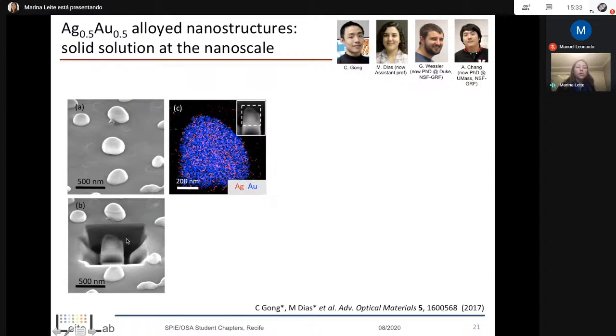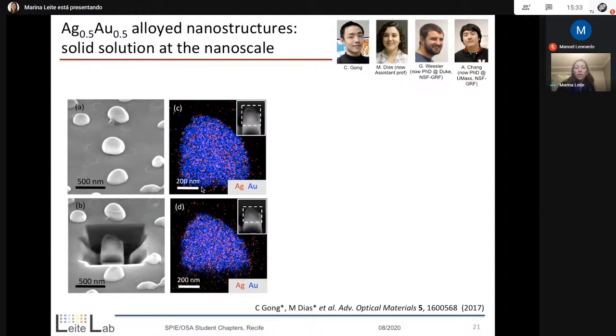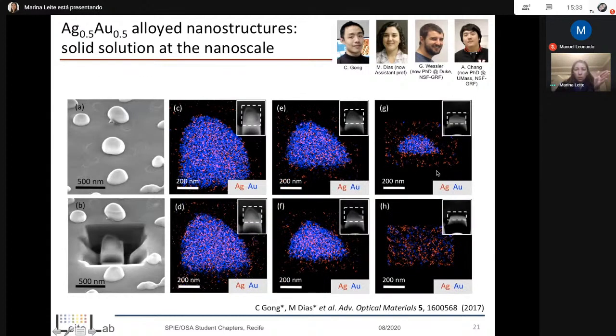And essentially what we do is that we mill the sample, so we use the focused ion beam so that we can remove layers, right? It's a tomographic technique in that sense, although destructive. We can essentially be removing the layers of the nanoparticle and be mapping the chemical composition as we go. So that's essentially what you're seeing. It's a map of the chemical composition distribution where we do see silver and gold uniformly distributed. And that happens for the entire particle, okay, after sectioning multiple times. So we do have an alloy, check.